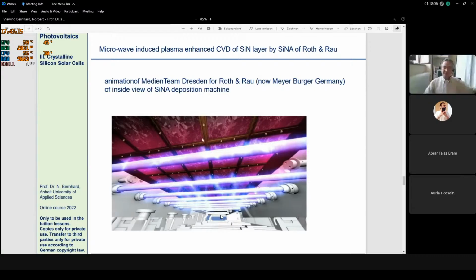The gas here again is silane and ammonia. And the same chemical reaction, which was described in my previous picture, is triggered here. You see here many wafers, in this case multicrystalline wafers, arranged in some sort of wafer array. And these wafers move continuously over these plasma generating tubes. This machine was built by Roth and Rau. Meanwhile, it's called Meyer Burger Germany, which is still a leading equipment manufacturer, especially for this kind of process.